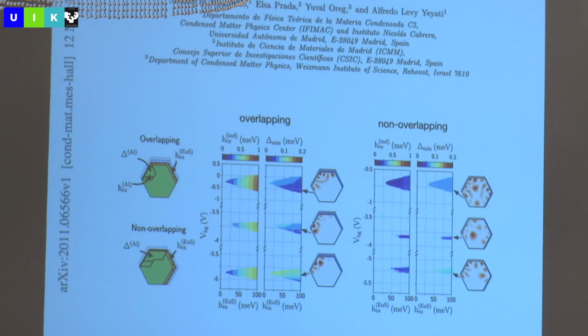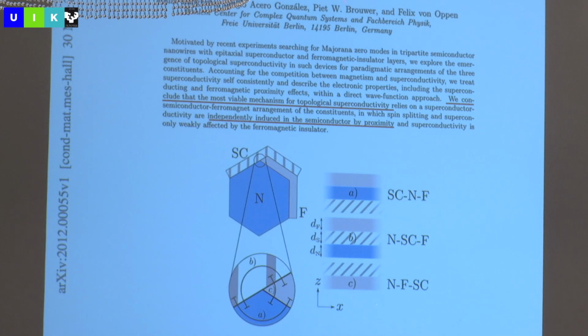And then here's another one which said, the same setup with different people, but similar analysis, finding the regions where there's a topological phase where the wave function can sit at the interface between these two materials. And when they're non-overlapping, it's very hard to find topological regions, although not impossible. But the topological regions were much more prevalent when they were overlapping. So here's another one from these students in